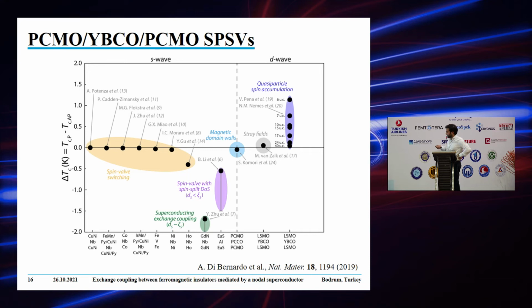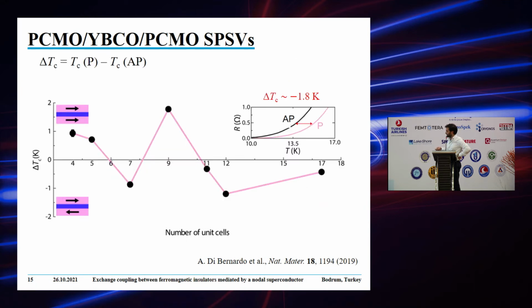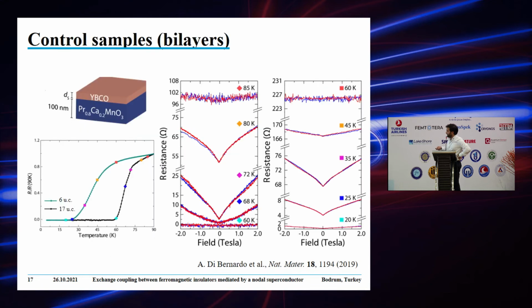So if you plot now this data, the delta TC seen in the literature for different types of systems, with our systems we can span both delta TC values that are positive and negative, and reach values as large as almost 2 Kelvin. So it's a very large delta TC that we observed for some of these spin valves, as you can see here. So we did some control experiments. We put just bilayers in this case, and there is nothing, there's just this V-shaped suppression of superconductivity due to the applied field.